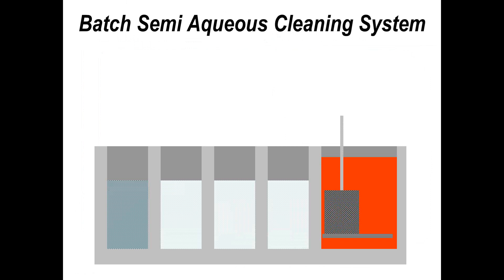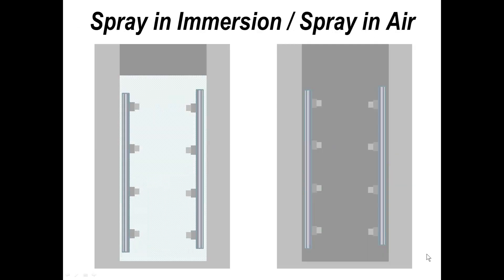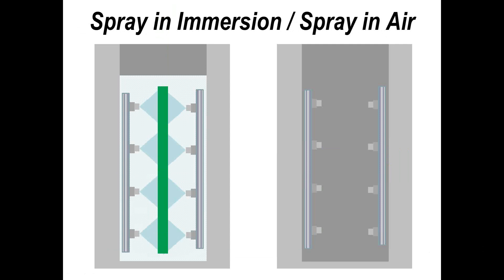Typically, the last stage in a batch cleaning process like this uses distilled water, which gives the highest level of cleanliness achievable. If you use tap water, because of the variation throughout different parts of the country, you will potentially suffer with inconsistency in cleaning performance. Spraying under immersion still assists the cleaning process even though the force of the jets is somewhat reduced. In contrast, standard spray in air delivers the full force of the jets directly onto the board surface.